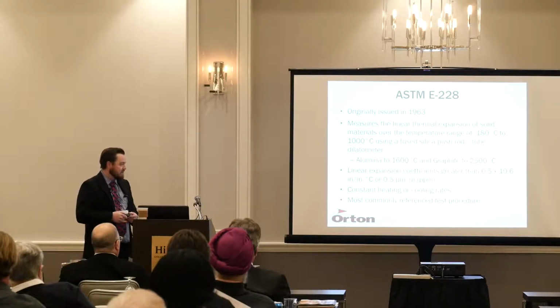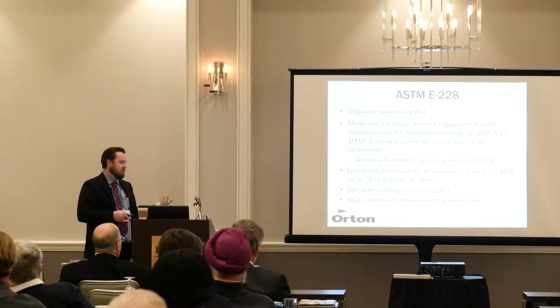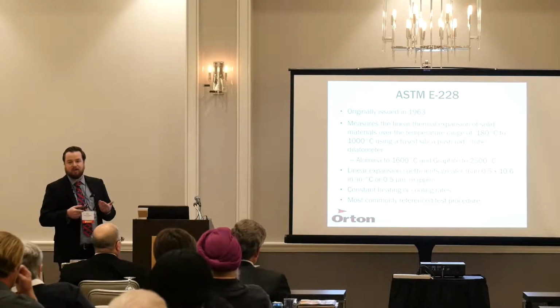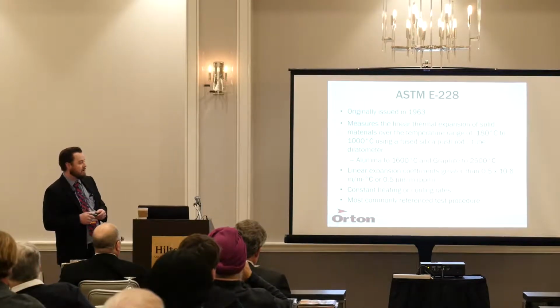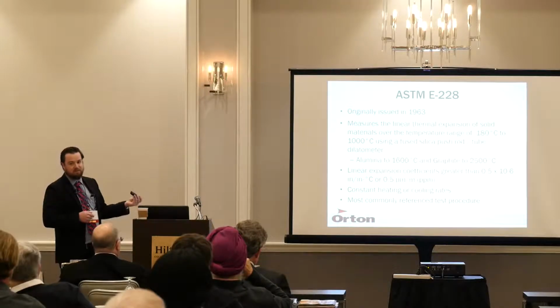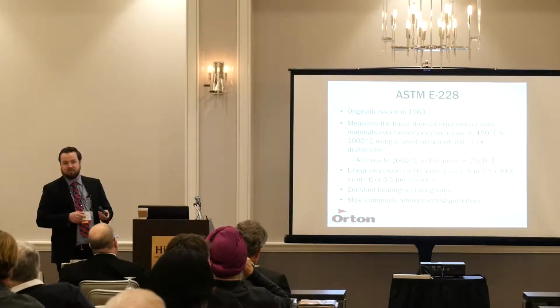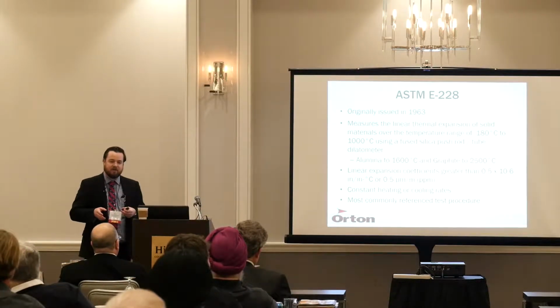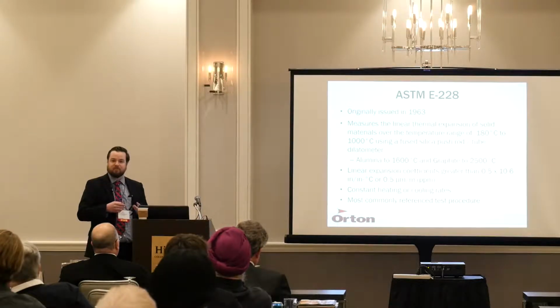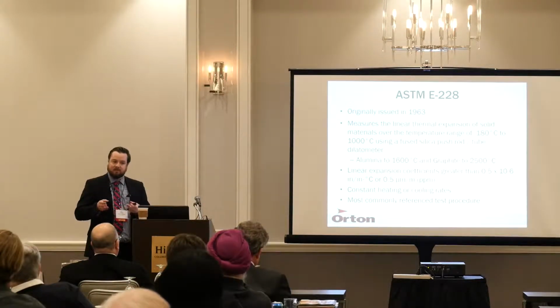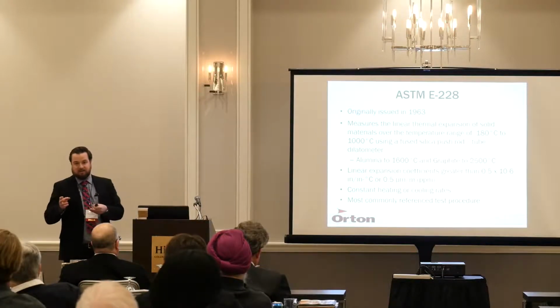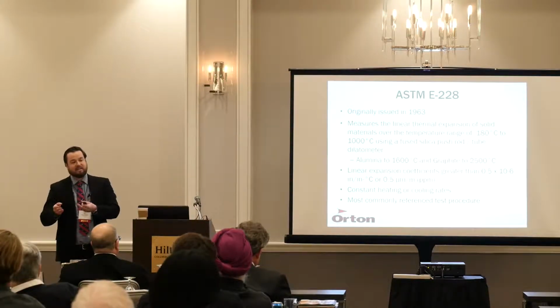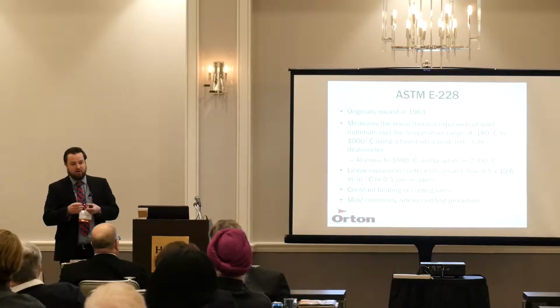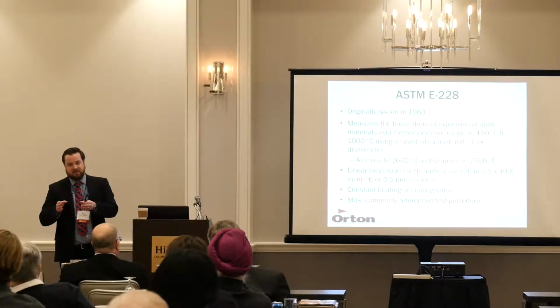As I said, these measurements are very small, so your linear expansion is typically referenced in parts per million, being not a concentration, but as a 10 to the negative 6 unit. So you have inches per inch per C, or centimeters per C. And that's because you're relating it to the sample length itself. It's a percentage. So it's not a tool that says you will be able to predict what your sample is going to see in the future, but the measurement's made per inch. So it's how long of a sample is contracting how much.